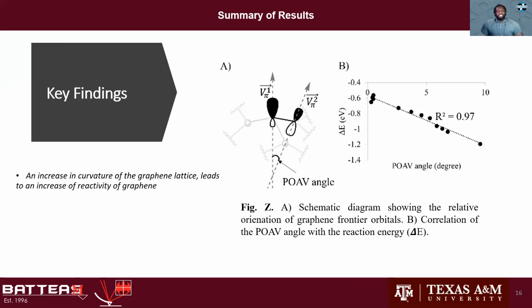And so just to reiterate, experimentally and computationally, we determined that controlled out-of-plane strain can be applied to graphene, and we see that with increasing curvature, this disrupts the in-plane delocalization of graphene, yielding a decrease in the activation barrier of the test reaction as a function of increasing curvature.